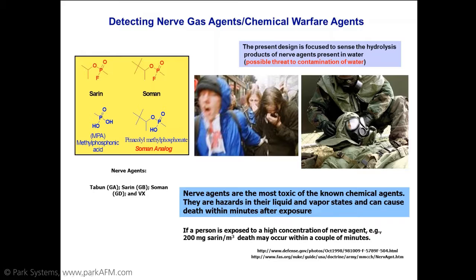For example, it takes about 200 milligrams of sarin per cubic meter to cause death within a couple of minutes. In other words, it's very toxic and also dangerous in the hands of the wrong people. However, we're interested in it, and obviously we cannot test the real thing. We have to utilize an analog. And we use methylphosphonic acid and pinacolyl methylphosphonate as a soman analog for all our tests.